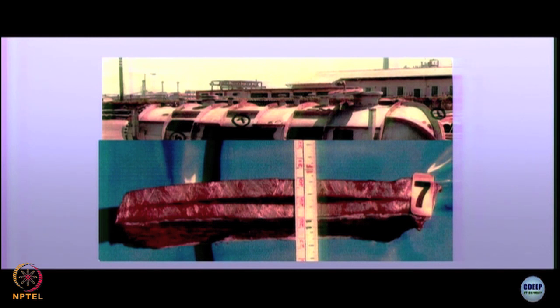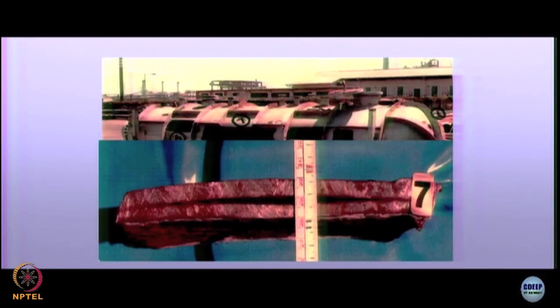Why does it happen? When you take a steel and put it in an environment, hydrogen evolves, there is a corrosion. But one more thing happens, the hydrogen enters the steel and gets into the material, it affects it. In this case, the hydrogen got accumulated. Now you see, we are getting to a different dimension of the problem. The primary cause is corrosion, the secondary cause is the real reason for failure. Had the hydrogen not gone into it, the corrosion was very minor. Now, this is a different kind of problem. How do you solve it? So, this is called a different mechanism. We call it hydrogen damage in the broader sense.